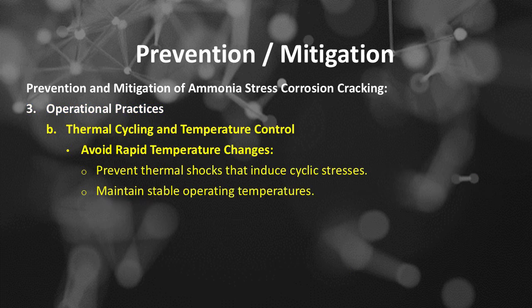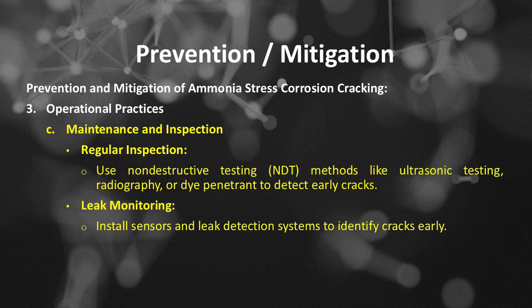Number B of operational practices is thermal cycling and temperature control. Avoid rapid temperature changes, prevent thermal shocks that induce cyclic stresses, and maintain stable operating temperatures. Operational practices. Number C is maintenance and inspection, which includes: the first is regular inspection, use non-destructive testing, NDT, methods like ultrasonic testing, radiography, or dye penetrant to detect early cracks. The second is leak monitoring, install sensors and leak detection systems to identify cracks early.